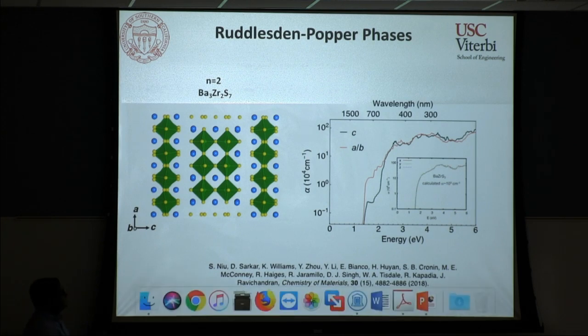So when we did the DFT calculations, what we found was that this system was a little more symmetric than we wanted. So in principle, it's going to be hard to find polar order. But nevertheless, what we found was that the optical absorption coefficient along the two-dimensional planes and across the two-dimensional planes were very, very different. And this, for some weird reason, red shifted the band gap from the 1.85 eV predicted value to 1.2 or 1.3 eV. So that means somehow you can take the three-dimensional perovskite and make a layered structure. In principle, you should actually increase your gap, but now you have shifted it to the other side, which is kind of unusual for us.